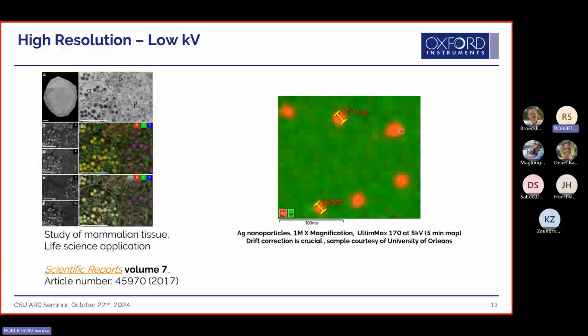But remember this one rule. If you can't see something in your SEM, you can't do X-ray mapping on it. So you need to do a good job of focusing on the SEM side as well, because that will allow you to improve the results you're getting. This one was at 1 million X magnification, and at that point, you will want to have drift correction because you're at a really high mag.